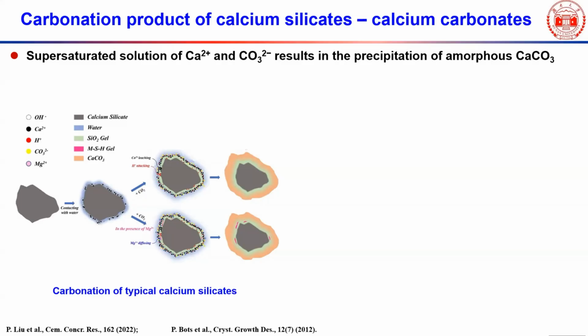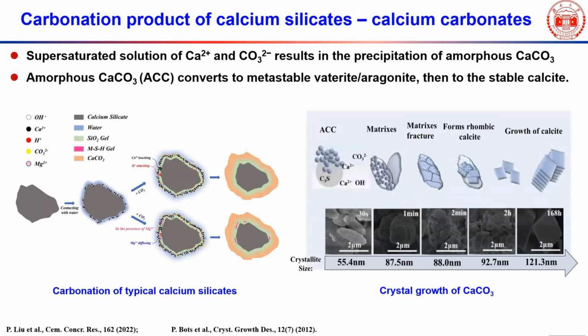Well, also, in a supersaturated solution of calcium hydroxide, calcium reacts with carbonate ions, resulting in the precipitation of amorphous calcium carbonate, even in the presence of moisture. And so you can see initially it will form amorphous calcium carbonate, and then with time, the crystal sizes of calcium carbonate start to grow.